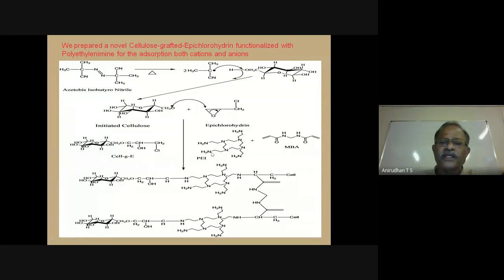And this again further reacts with polyethylenimine. We have introduced an amino group. So the NH2 group is the amino group we have introduced, and it will react with a cross-linking agent like methylene bisacrylamide, and we have a very good structure. You see that structure with amino functional group. So we start with cellulose only having primary and secondary alcoholic OH groups, and convert it into a material associated with an amino group.